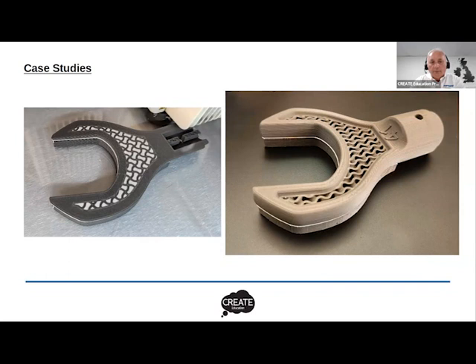And what you can see is I've created an infill pattern in the central part of this particular tool, again where I knew that the stress levels were low. So instead of printing it completely solid, it's printed with this gyroid infill. That's really allowed me to take material out of the part, which reduced the cost quite significantly. I think I brought the cost down by about 25%, and it's eliminated the reason for that crack developing that I showed in the previous slide.